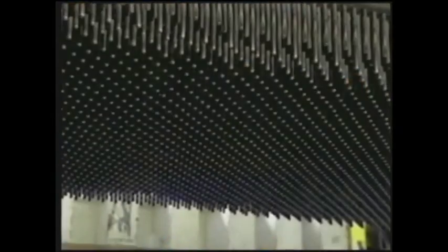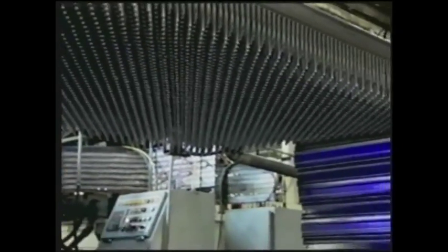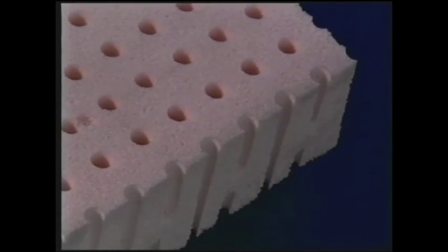You can recognize a product made by the Talalay process by the large number of pencil-sized holes formed by the pins in the lid and base of the mould. These pins ensure the vital changes in temperature are carried to the heart of the product during the heat exchange process. Take a closer look at Dunlopillo Talalay Latex and you'll see a fascinating uniform open cell structure.